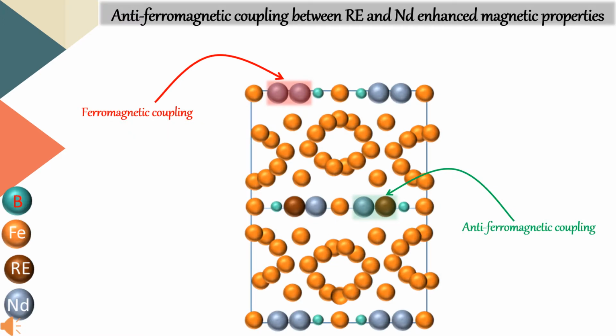The reason behind the enhancement of the magnetic properties is the ferro and antiferromagnetic coupling between the rare earth elements. When there is only Nd in the NdFeB crystal lattice, the Nd and the iron are both ferromagnetically coupled to each other. But when we substitute with some heavy rare earth like Dy and Tb, they couple to the Nd and iron antiferromagnetically, and because of this antiferromagnetic coupling, the anisotropy energy of the crystal is increased. So overall the magnetic properties increase. And the boron in the crystal lattice is non-magnetic, so it doesn't play any role in the enhancement or reduction of the magnetic properties during the substitution reactions.